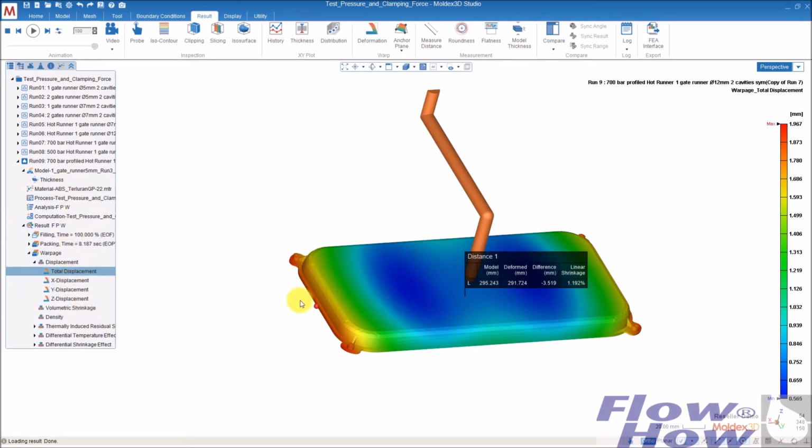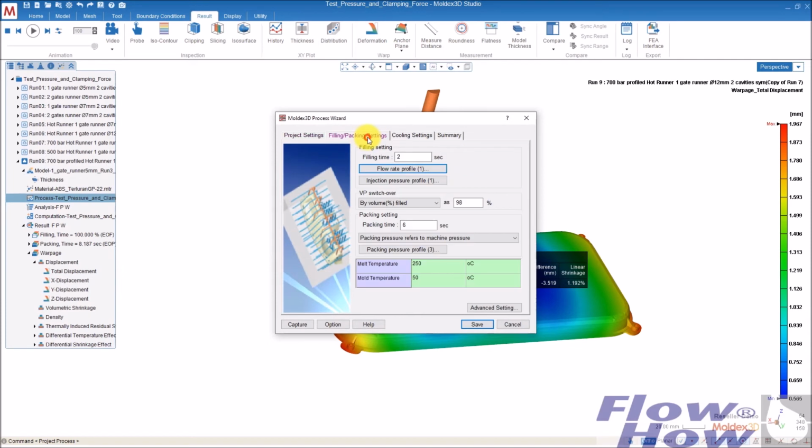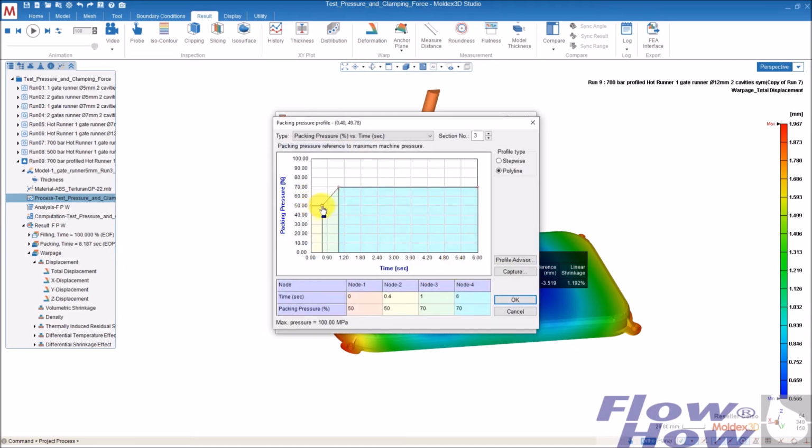And I made this profile where for the first half second or 0.4 second I have 500 bar, so I don't exceed the 350 ton. And then I increase the packing pressure from 500 to 700 bar and keep it for the last 5 seconds. So the first second is the only one that I profile, the rest is the same. That's also why the shrinkage is nearly the same. But actually doing this has a huge influence on the